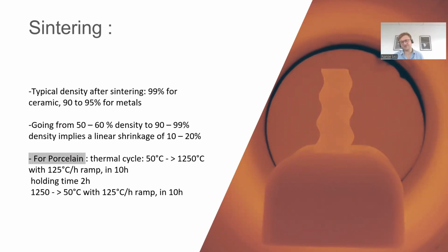The specificity with porcelain is this two-stage sintering: a first firing to get a porous structure, then glazing, then the second sintering. And the second specificity for porcelain is that the temperature is much, much lower, and we'll see that this is really important.